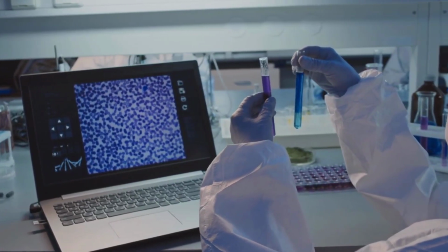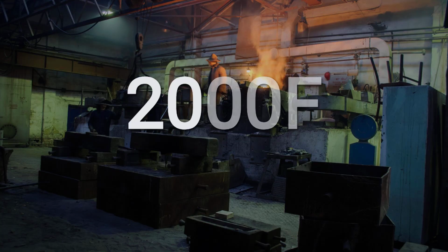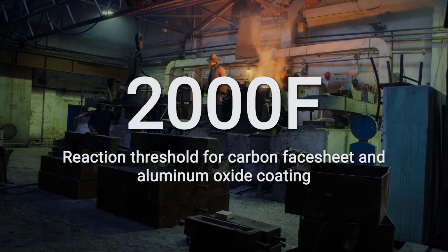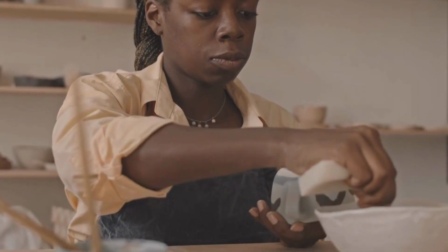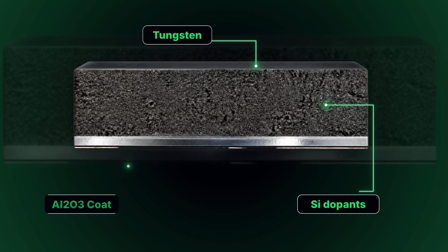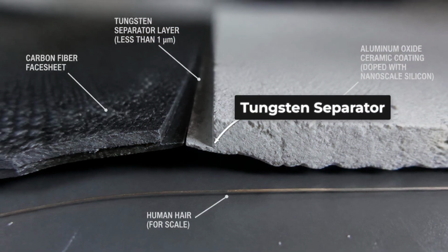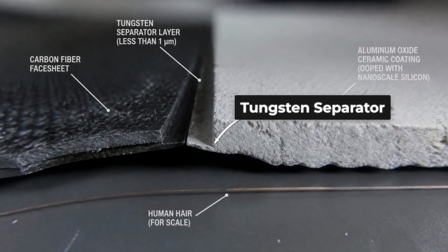However, spraying the ceramic directly onto raw carbon creates a volatile chemical hazard. At temperatures above 2,000 degrees Fahrenheit, carbon and aluminum oxide react, causing a chemical breakdown that darkens the surface and destroys its reflectivity. To isolate these materials, engineers deposited a thin tungsten separator layer, thinner than a human hair, directly between the carbon face sheet and the ceramic coating.